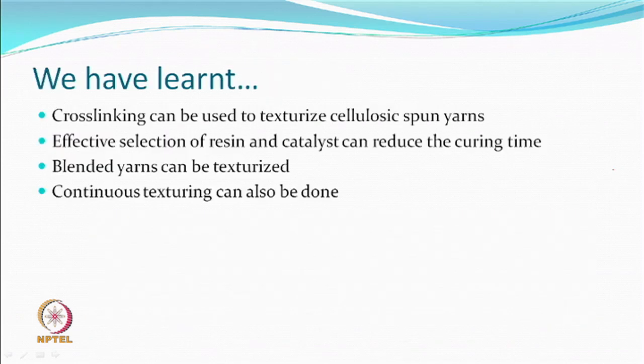So what we have learnt is that cross-linking can be used to texturize cellulosic spun yarns. Effective selection of resin and catalyst can reduce curing time. Blended yarn can be texturized. Continuous texturing can also be done. So some conclusion from that point of view.